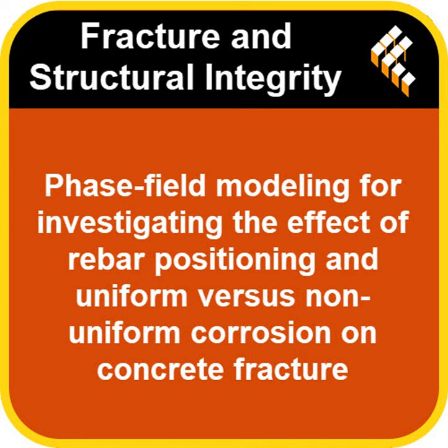Now, non-uniform corrosion. That sounds like it could be trickier. How'd they model that? They used a kind of lopsided model, specifically a semi-elliptical shape, to represent it. Imagine the rust expansion being much greater at one point around the rebar and much, much smaller at another point. In their simulations, the minimum displacement was only about 1/30th of the maximum. Whoa, so it's really bulging out in one spot, but hardly changing elsewhere. Pretty much. And they also considered how the position within the concrete cross-section mattered for this, so whether the maximum bulge was pointing towards the surface or sideways or inwards. Right, because that uneven pressure would interact differently with the surrounding concrete depending on which way it's pushing hardest. Exactly. Position P1 versus P2 in their diagrams showed this difference clearly.